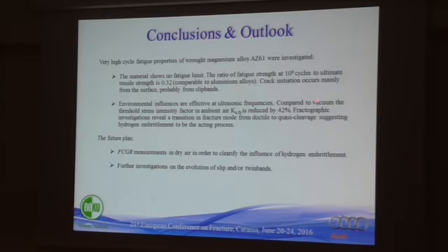We found a pronounced reduction in the threshold stress intensity factor in ambient air compared to vacuum of about 42%. And fractographic investigations reveal a transition in fracture mode from ductile to quasi-cleavage, suggesting most likely hydrogen embrittlement to be the acting process. So, the future plan: we'd like to conduct further fatigue crack growth rate measurements in dry air in order to answer the question whether it is hydrogen embrittlement or something else.